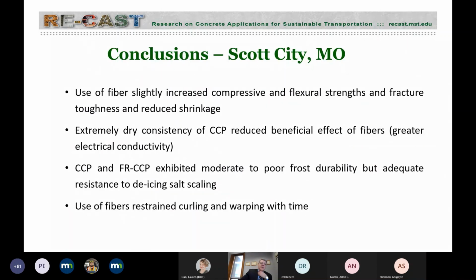So what we could learn as a conclusion from this second case study is that the use of fibers slightly increased compressive strength, actually considerably increased compressive strength and flexural strength at a certain age, but not later on. But it improved the flexural toughness, and you saw that the residual strength was about 15% versus 0 without fibers, and then contributed also to reduction of shrinkage. Because again, the CCP, despite the admixtures that improve rideability and surface finishing